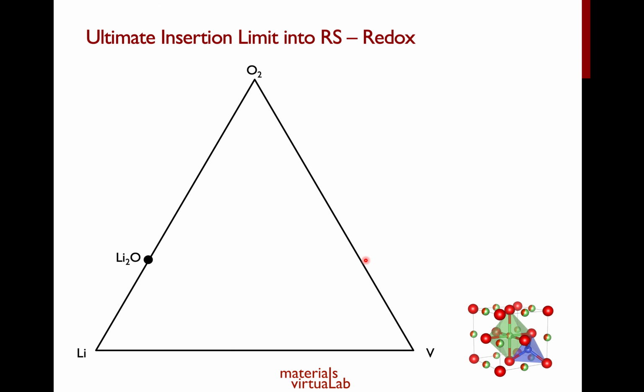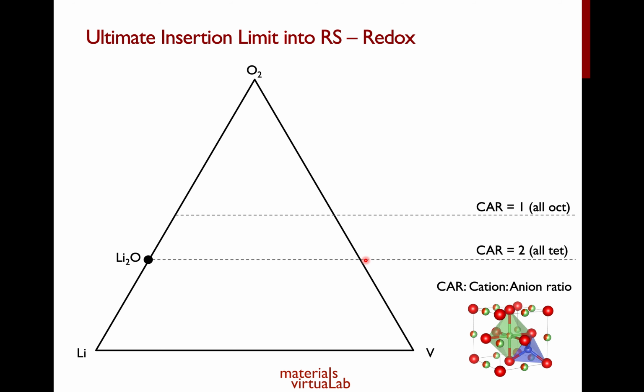So again, let me go back to a more simplified version of our lithium vanadium oxygen phase diagram. We can first draw two contours in terms of our cation to anion ratio. Remember, when you occupy all the octahedrals, you have a cation to anion ratio of 1. When you occupy all the tetrahedrals, like in Li2O, you have a cation to anion ratio of 2. I'm also going to draw here the vanadium 2+ limit. Let us assume that we can only lithiate our vanadates up to vanadium 2+. Even though vanadium 1+ is known, it is not a very common oxidation state. Let's set vanadium 2+ as our limit.